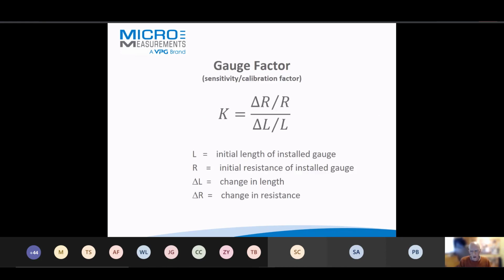We mentioned the strain gauge is measuring strain, and we want to find out the sensitivity or calibration factor of the gauge. This is done statistically through an ASTM test standard, where we bond the gauge to a special beam, apply a known strain, and measure the resistance change. So this gauge factor, the thing we're interested in, is a function of the change of resistance versus the original resistance over the change of length over the length. And of course, this is a microstrain, or strictly it's strain in this equation. So if we apply a known value here and measure the value here, we can calculate gauge factor. And this is a statistical number that comes with the gauges that you purchase.